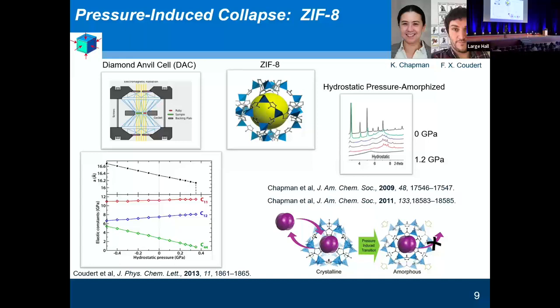So then she went on and did some beautiful research on trapping iodine within a crystalline system, then ball milling it, very quickly amorphizing it and preventing the iodine from leaving. So that's kind of trapping guests within MOF systems. So François-Xavier Coudert has actually shown the mechanism of collapse of these ZIFs is usually via shear collapse. Again, even though we're applying hydrostatic compression, it's always in our systems, one elastic tensor that seems to drop off more.